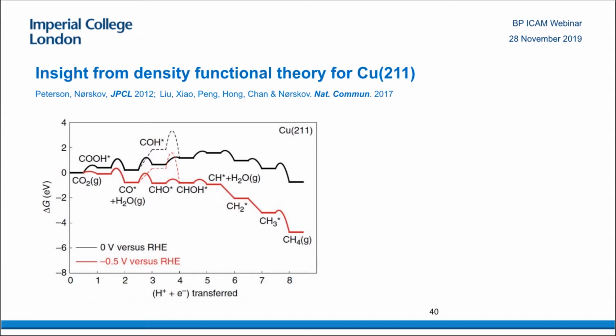That is going from CO to CHO. There's a very big barrier between the steps. So you can imagine the ideal way of catalyzing the reaction better would be to completely flatten this curve. Then you'd be able to operate with minimal potential losses. You can imagine you'd want to stabilize these transition states and maybe some of these intermediate states as well.